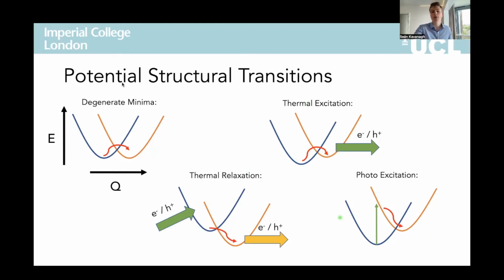The final case to mention is the potential for photoexcitation from the defect ground state to the metastable state, which could certainly occur under standard operating conditions for solar cell materials, where we have an ample supply of photons in the material, with this now depending on other properties such as the photoionization cross-section or transition dipole moment between these states.